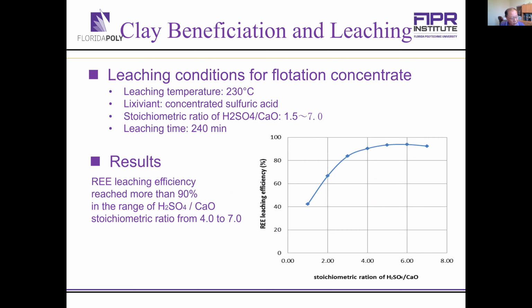As I point out, when we did the leaching directly on the cyclone underflow, the recovery was not very high, it's 55%. So in this case, we increased the temperature and also the concentration of sulfuric acid. In so doing, we increased the leaching recovery to over 80%.